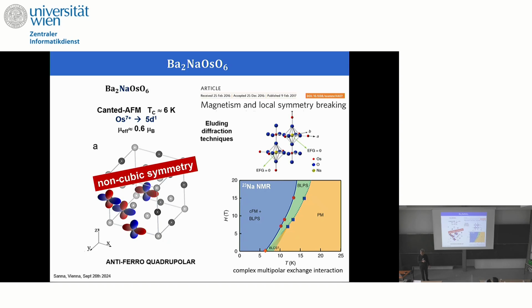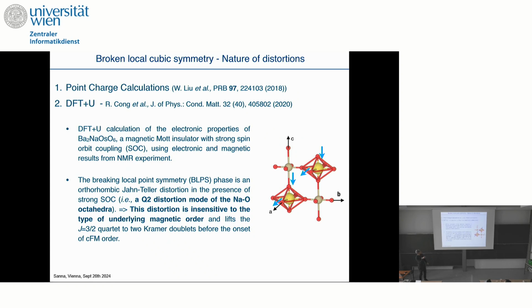This experimental report on nuclear magnetic resonance results on sodium said that the magnetic region is anticipated by local distortions in the phase diagram, which can be related to an antiferro-quadrupolar ordering in this material. Okay, Sanna continued by studying better what kind of distortions are at play, also from the experimental point of view.